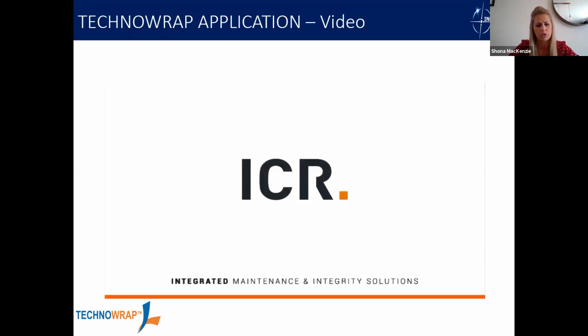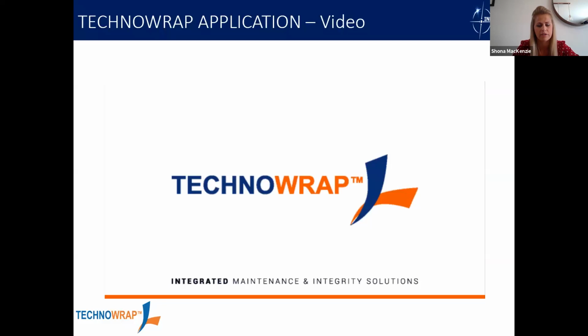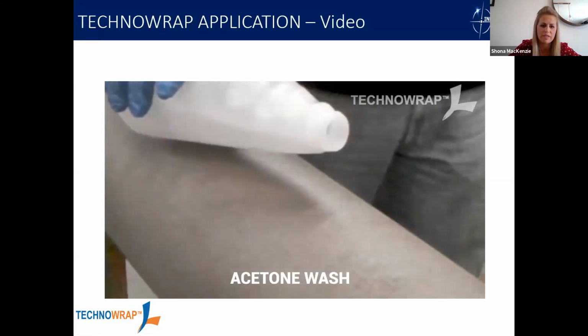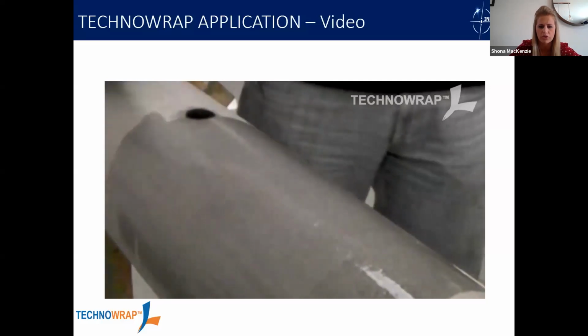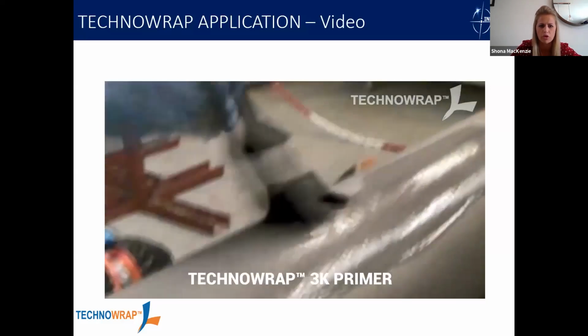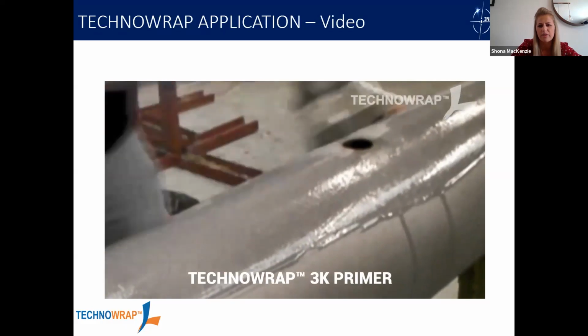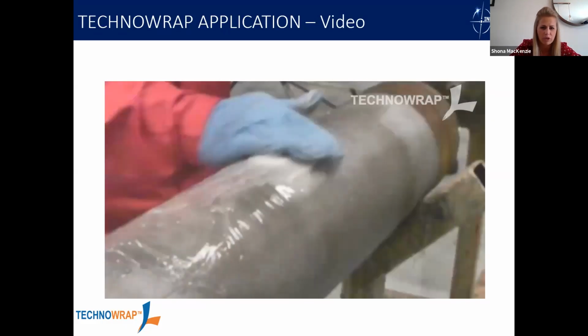Now, not all repair providers will apply their layers in stages, so we tend to do 2 layers as the first application, and then we do a compression in between layers. We'll do a low load cure in between, so not a full cure, but just enough to make sure that there's no air pockets in between and that we've got good compression between the layers. So it essentially just promotes a better quality adhesive through the layers of the composite.